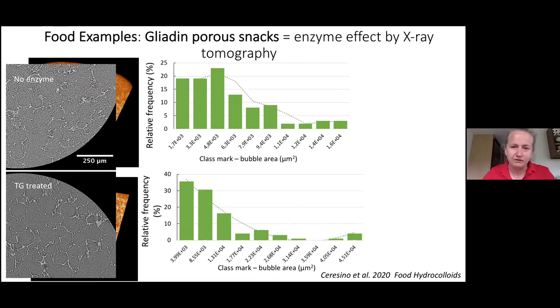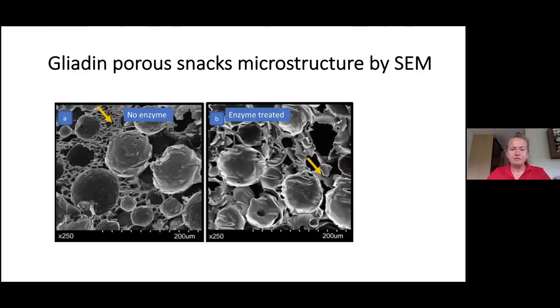We observed that by introducing a transglutaminase, of course, one is expecting that the proteins will get cross-linked. But beside that, we also observed differences in porosity and the sizes of the bubbles formed. So the down curve is showing the higher and bigger sizes of the bubbles. In the snacks microstructure, we also observed in these particular samples different interfacial structures, as you can see pointed out with the yellow arrows: no enzyme having the more irregular structure, while enzyme treated has kind of sheets holding bubbles together.